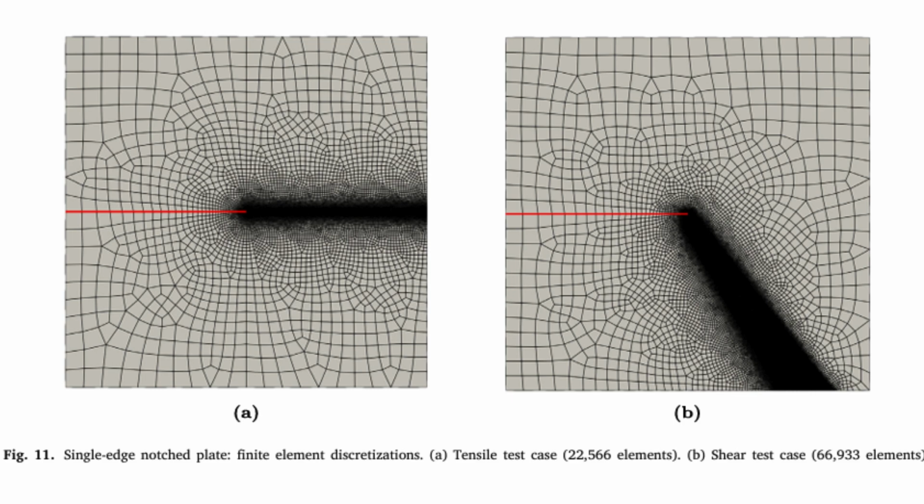And what about the line search? Was it actually needed? Did LBFGS fail without it? Oh, absolutely critical. The experiments confirmed it. In the problems known for unstable crack propagation, like the SNPT, tension notch, and S3PBT bending, the LBFGS algorithm without the gradient-based line search simply diverged. It crashed as soon as the crack growth became unstable. So the line search was the essential safety net that made LBFGS usable for these problems. Non-negotiable. It provided the robustness that LBFGS inherently lacks in these non-convex history-dependent situations.